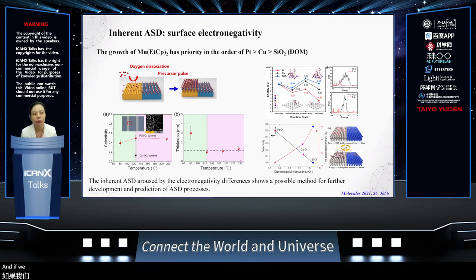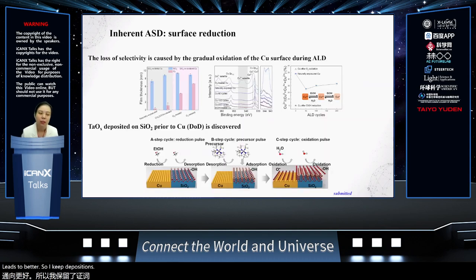And if we really compare different surfaces, the surface electronegativity is in the order of platinum larger than copper, and definitely larger than this kind of oxide, leading to better selective deposition. So next, something in more detail compared with the dielectric-on-dielectric that I showed you from the industry applications. Actually, the difficulty here is that, as I just mentioned, deposition on the metal side for these kinds of precursors is easier compared to on the oxide. So we have to really invert these processes.